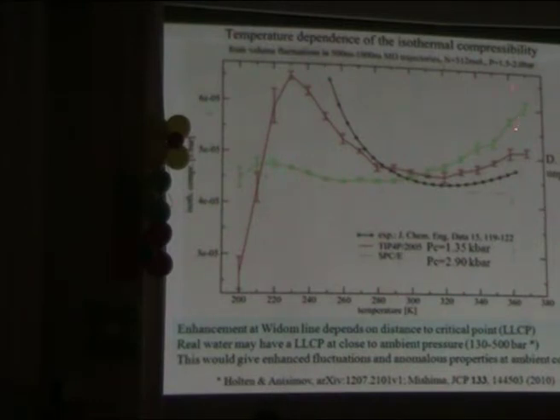Now, if we take another model, the SPC/E, it has a much flatter maximum down here. So here's the Widom line at ambient pressure for SPC/E water. Now, the enhancement will depend on the vicinity of the critical point, how far away. At the critical point, we would have a strict divergence. Now, the critical point for TIP4P 2005 water is at 1.35 kilobar, but for SPC/E, it's at 2.9 kilobar. So we have a much smaller enhancement for SPC/E, much bigger for TIP4P 2005.